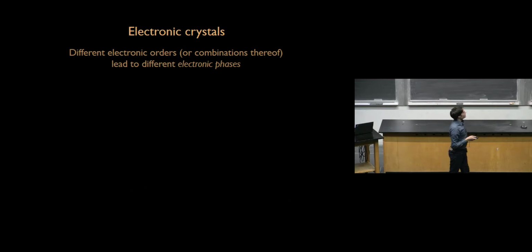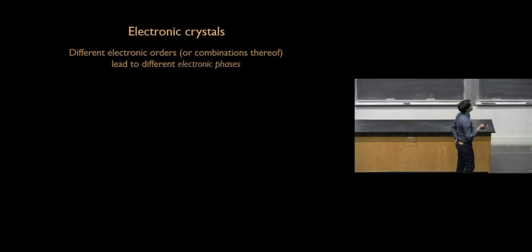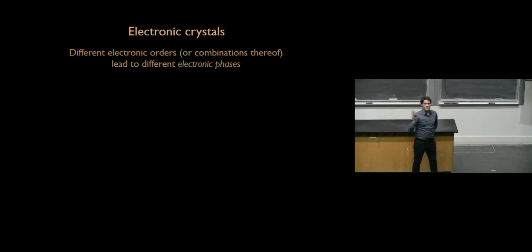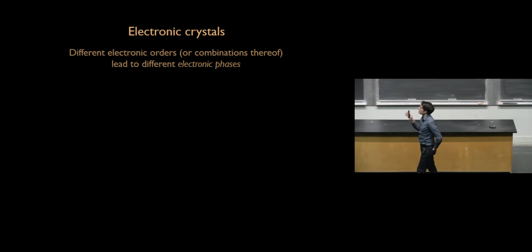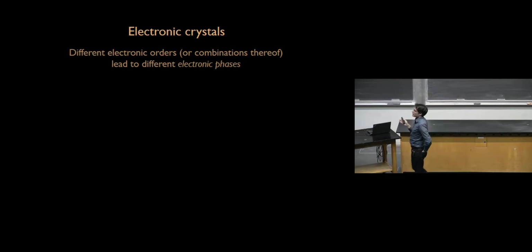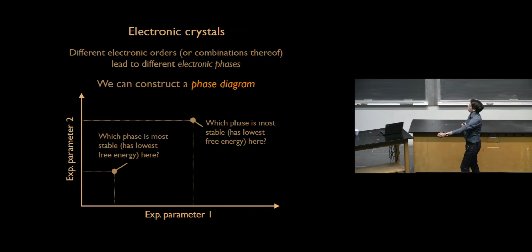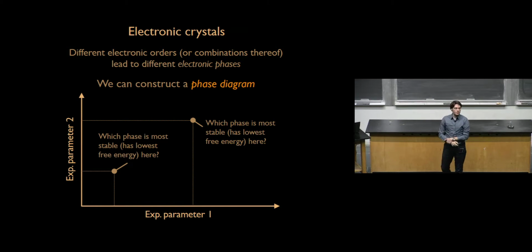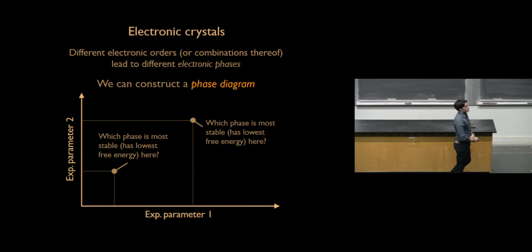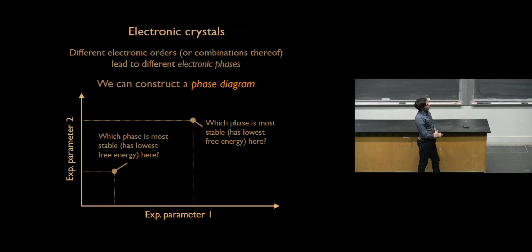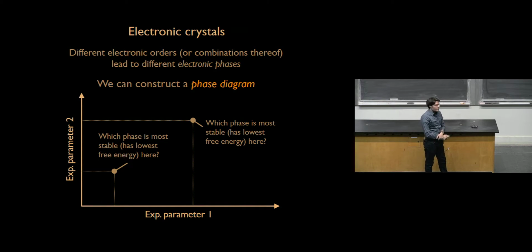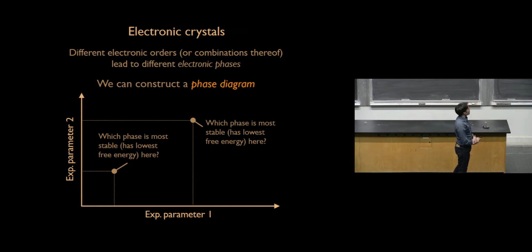So now, what we know is that different electronic orders, or combinations of multiple types of electronic orders, lead to different or emergent electronic phases. So what we do in condensed matter, when we study these types of quantum materials that have these exotic types of electronic orders, is construct a phase diagram. The phase diagram is 90% of the time a function of 2 experimental parameters, and 99% of the time this vertical axis is temperature. You will see that more clearly later. But we have 2 experimental parameters, and we go around in this phase diagram.